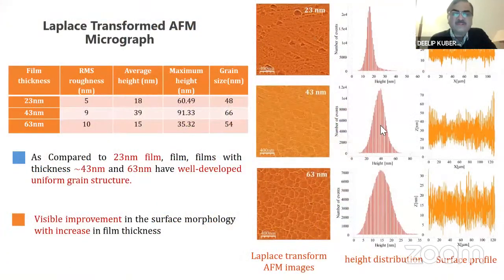So with the film thickness, the grain morphology becomes more and more uniform. And then you can find out the film thickness as 23 nanometers. And if you have a higher thickness film, a well-developed uniform grain structure takes place. As the thickness increases, the grain structure becomes more and more uniform.